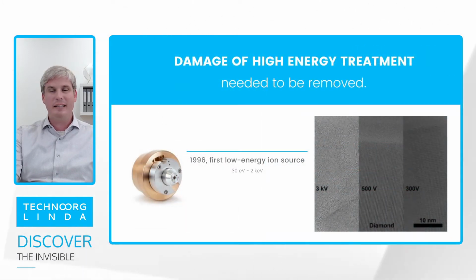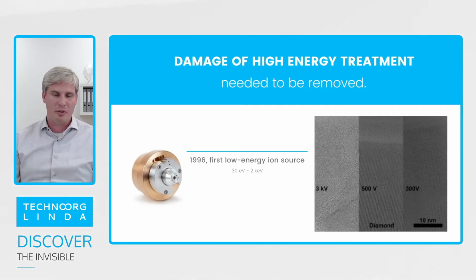And in 1996, a new invention came, the first dedicated low energy ion source on the market, from the team of Technorg Linda, Hungary. That ion source operated below 2 keV, and in high vacuum circumstances, even 20 or 30 electron volts can be used, for example in Auger systems. But in normal mid-vacuum, usually we go down to 100, 200 electron volts. But it's a great tool for cleaning those amorphous and damaged layers caused by any previous steps of preparation, including the high energy ion bombardment.